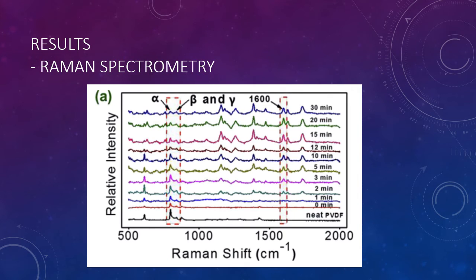By the Raman spectrometry, the thing worth noticing is the 1600 per centimeter Raman shift. 1600 refers to the 1,4-para substituted benzene ring, which is the LCP nanoparticles in the sample. As you can see throughout the experiment, there is a very significant increment of LCP content because of the continuous sliding effect in the steady state. The peak at the 15th minute and 20th minute is higher than the others.